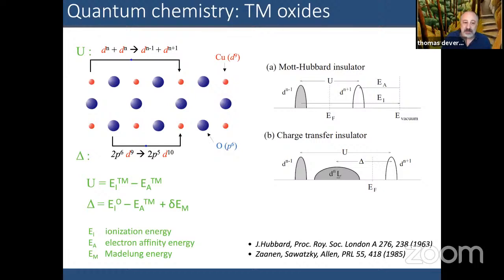Okay, so this is just an entry point. I think that this is well known in our community that in transition metal oxides, there's two flavors that we would think about in terms of the parent compounds being insulators. The energy scales are the charge transfer energy to put an electron from the ligand onto the transition metal, and the Hubbard U that characterizes the ionization energy and the electron affinity to create a d^n ground state, to go from d^n to d^(n-1) or d^(n+1). And the categorization is just basically whether U and delta flip priority.